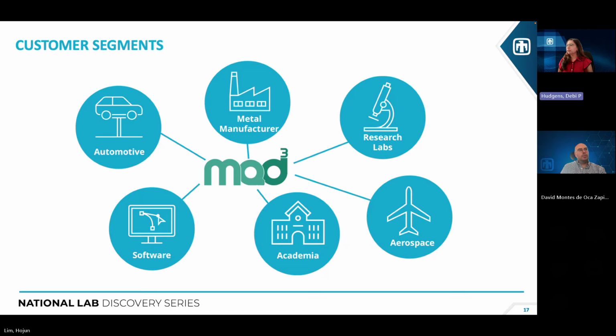Okay. There was a question that we received, whether the model includes anything about grain size and shape. Yes. One of our assumptions was that crystallographic texture dominates the plastic anisotropy effect. We did some tests with varying grain sizes and shapes, but the current version of MAD³ does not consider grain shapes and sizes. You can find a little more detail in our papers, so you'll see how much that affected anisotropy behavior. But we thought the dominant factor is the crystallographic orientation, or the texture.